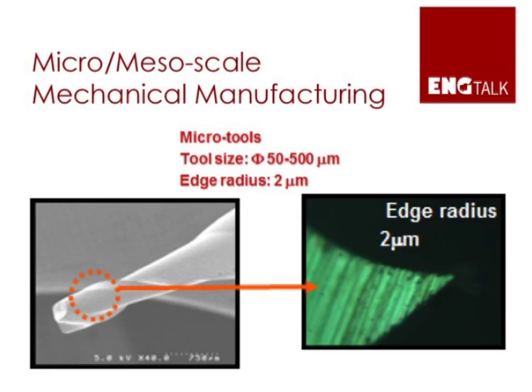What you see is a two-fluted tungsten carbide tool. The diameters of these tools could be anywhere between 50 microns to 500 microns. To give you a size scale, 100 microns is roughly the diameter of your hair. The key thing to notice here is the edge of the tool — the edge radius — which essentially dictates how sharp the tool is. In this particular case it is around 2 microns, and that's typically the edge radius that we see in these tungsten carbide tools.